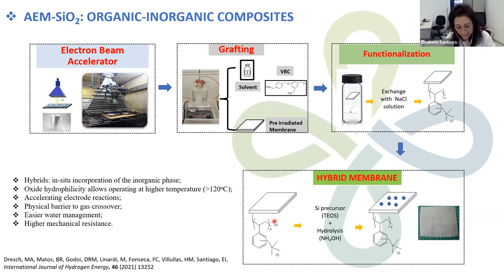So here, in this case, you have the membrane, AEM, produced by pre-irradiation, and then you have grafting, functionalization, and the hybrid. The membrane is submitted to a hydrolysis of a silicon precursor in the presence of ammonium. So in this case, you can put everything together, stay a little bit, and you have an incorporation of the silica in the pores or in the ionic clusters of this membrane. So that's the resulting membrane.